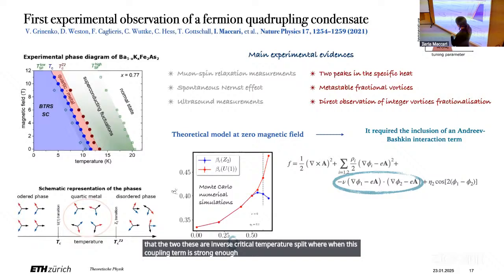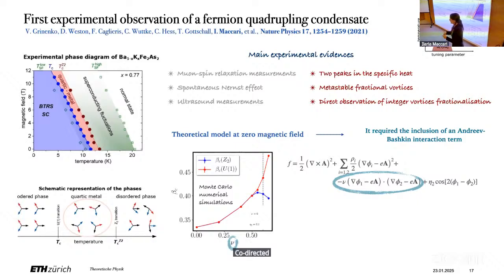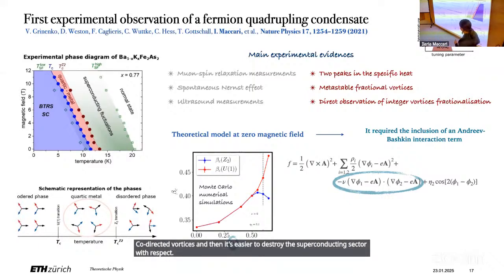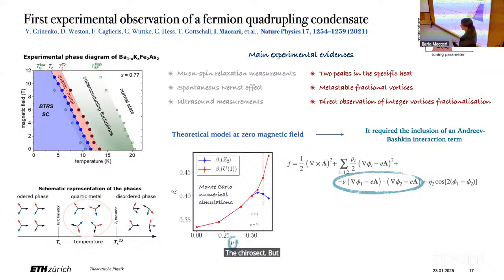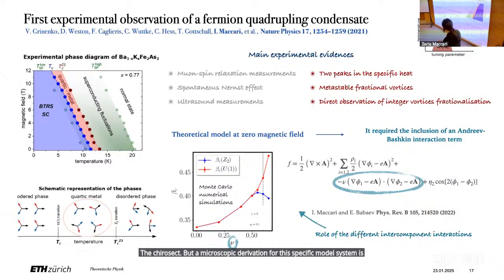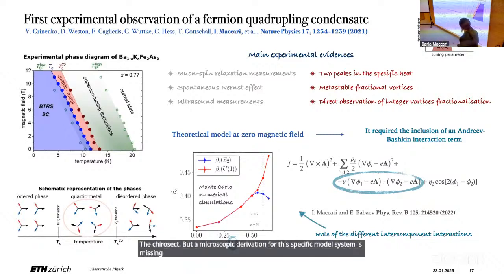Essentially, this term here is favoring the co-flow of the components. So of course, it favors the proliferation of co-directed vortices, and then it's easier to destroy the superconducting sector with respect to the chiral sector. But a microscopic derivation for this specific model is missing. And more details can be found in this paper.